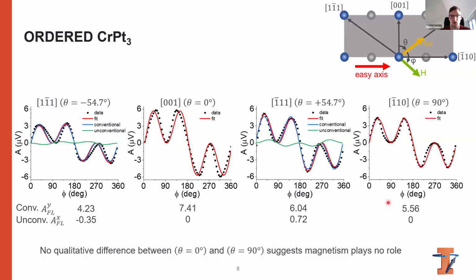However, we also looked at the 90-degree case where the current is parallel to the magnetic easy axis, and this is where we would expect the largest unconventional torque. But what we actually see is there's no qualitative difference between 0 and 90 degrees, so this already suggests that magnetism doesn't play a role in generating these torques.